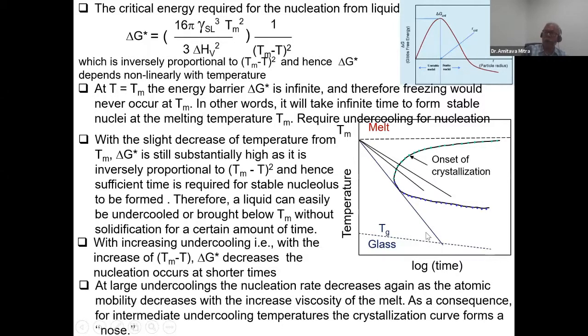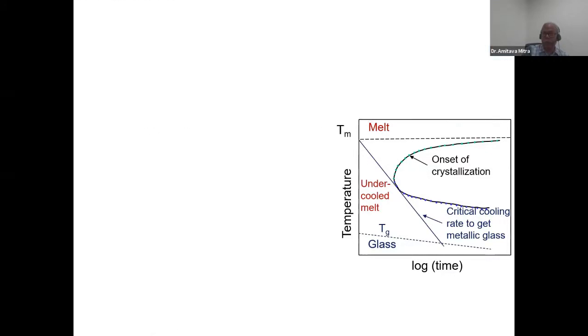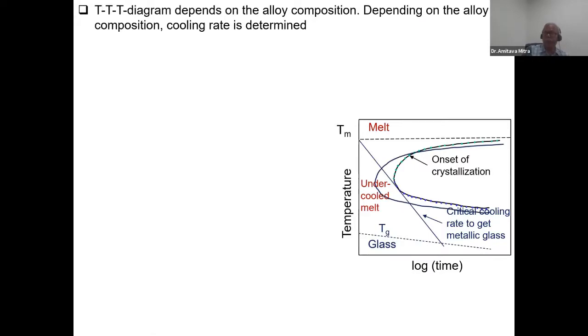So at which temperature and which rate we'll do this will be determined by this TTT curve, and depending on the composition, the TTT curve for this undercooled melt changes. This is a single composition. If my TTT curve is like that, we require a much faster cooling rate, and if my TTT curve is like that, we need a much slower cooling rate for going from the melt to a glassy state.